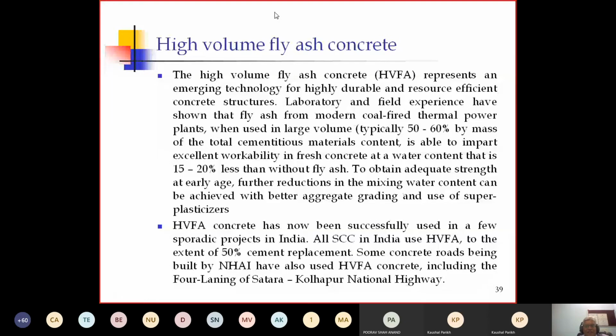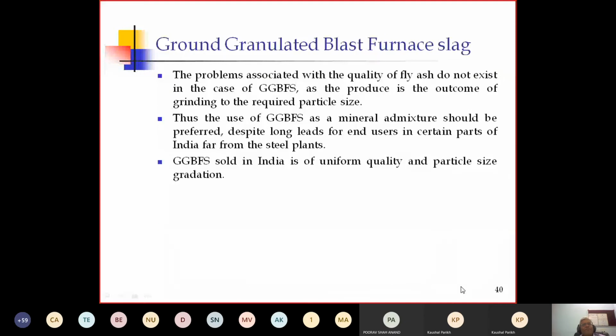High volume fly ash concrete has now been successfully used in a few projects in India. All self-compacting concrete in India uses high volume fly ash concrete to the extent of 50% cement replacement. Some concrete roads being built by the NHAI have also used high volume fly ash concrete, including the 4-laning of the Satara Kolhapur National Highway project. So in many national highway projects, in the pavement, they are using high volume fly ash concrete, where fly ash is in the range of 50 to 60% replacement of the cement.